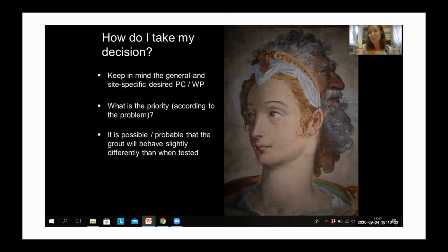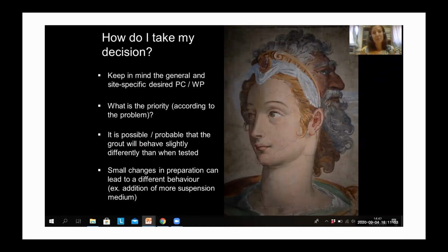And also it's very important to remember that it's possible, and I would say it's probable, that the grout will behave slightly differently than when tested, because of course you can try to make replicas of your original plaster, but it's never going to be the same. We know that the porosity can be similar, but it's never going to be the same. Of course, there will be no aging because it's a newly produced plaster. And so of course it's very informative, it's highly needed testing, but it may be slightly different when actually implemented then on site. And also we need to remember that small changes in preparation can lead to a different behavior. So I can't just add a bit more water so that I can inject more easily, because then I need to expect that the behavior will be different.